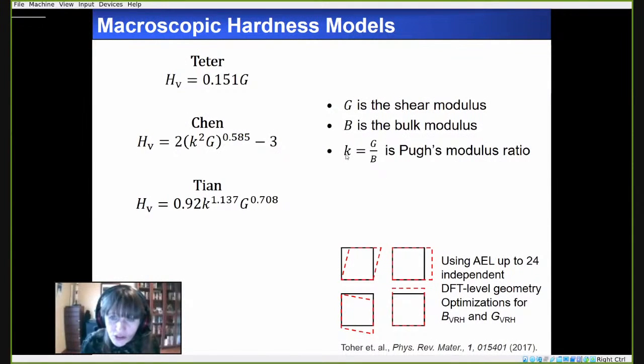Now, in these other models, you see that they use the K, which is the shear modulus divided by the bulk modulus. So if your bulk modulus is much too low, then your K is going to be much too high, and your Vickers hardness just explodes. And so in some cases, we just got unreasonably high Vickers hardnesses for these crystal structures that were hypothetical, generated in the crystal structure prediction search. They might not ever exist. And because of that, they were found to have a very high Vickers hardness, like 200, 300 gigapascals. And they were then found to be predominant in the breeding pool in the search. So that is the main reason why we chose the Teter model.